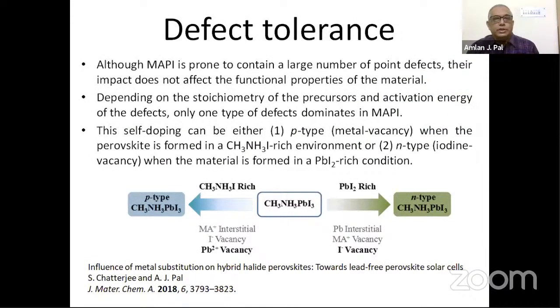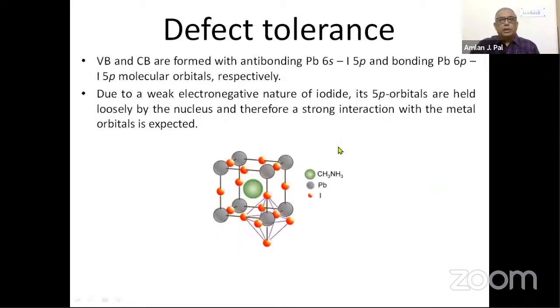And the defect tolerance. I said that, of course, since we are making the material through a solution process, the material is prone to contain a large number of defects. But fortunately, these defects do not affect the functional properties of the material. Why? Because depending on the stoichiometry of the precursors and the activation energies, self-doping can be done.